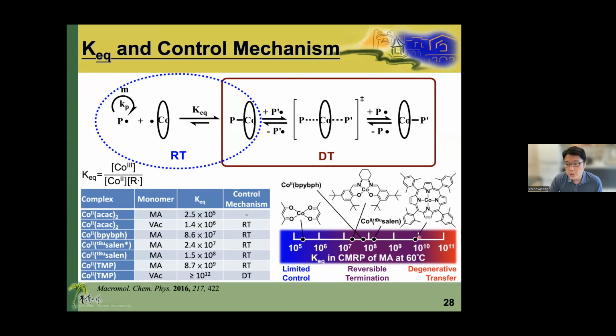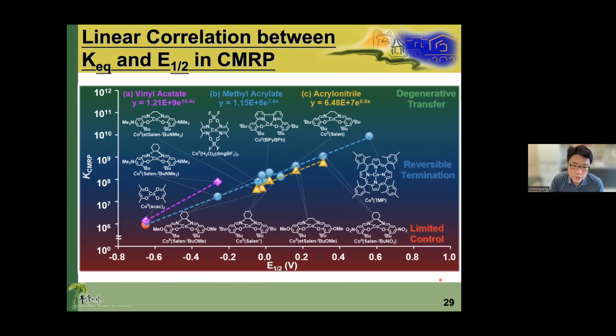And if the equilibrium constant goes higher, then you will see this cobalt-carbon bond is too strong, so that it cannot self-dissociate to generate radical. So it requires an external radical to kick out the original radical by the trans effect. So now at this stage, the polymerization will be mediated by this degenerative transfer polymerization. Then we collect more data. Of course, thanks to my hardworking student, we obtained this figure, and you can see with methyl acrylate polymerization, we got the linear correlation between the redox potential and the equilibrium constant. And with other monomers, we also observed a similar thing. So we believe we understand the mechanism pretty well.